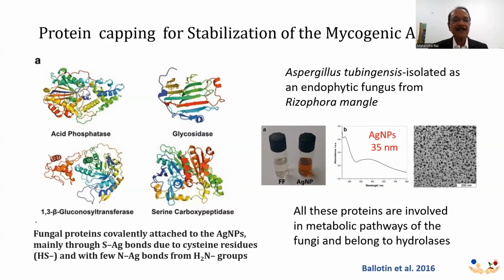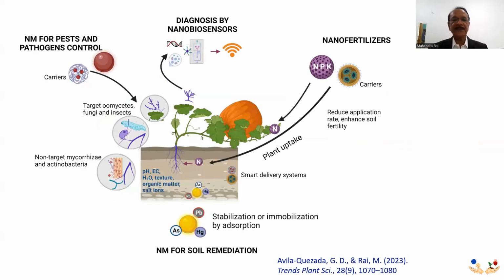When the proteins on the caps of the nanoparticles were analyzed, it was found that the capping is due to acid phosphatase enzymes, glycosidase, 1,3-beta-gluconosyltransferase, and serine carboxypeptidase. These are the enzymes, proteins responsible for capping of silver nanoparticles. And these cappings are attached to the silver nanoparticle with sulfhydryl groups. All these proteins are involved in metabolic pathways of fungi and belong to hydrolases.